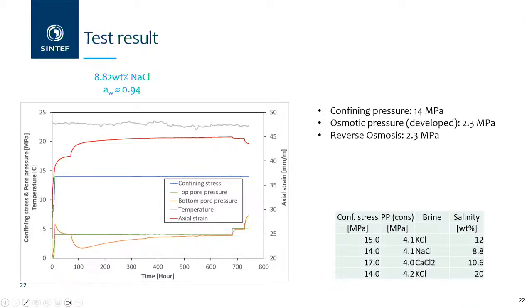Immediately, not immediately, the pressure starts to drop because it's sucking the water from the shale. And then when the water fluid reaches the end of the sample, this hydraulic diffusivity goes down or off, and the ionic diffusivity starts, and eventually it comes back to equilibrium again. In this test, I just exposed the sample to fresh water to see if I can get back the compaction. This is the compaction, how much the sample compacted. And I ended up with, okay, I lost, the pressure went down to 2.3, but when I exposed it to water, it also gained 2.3.